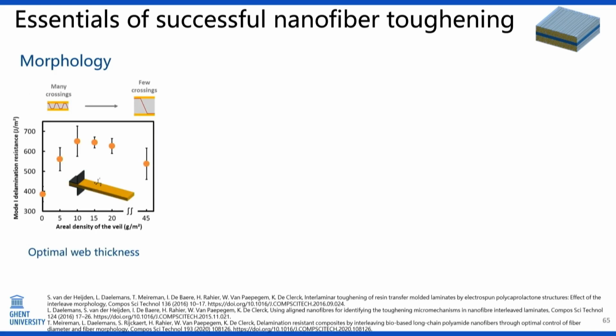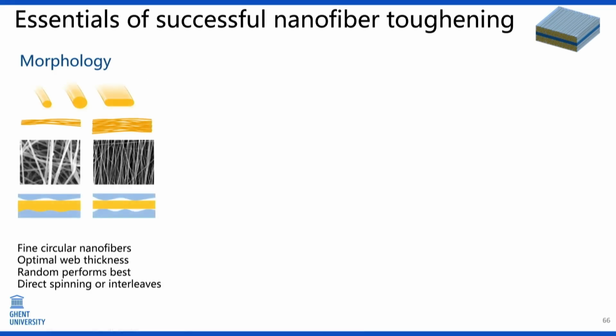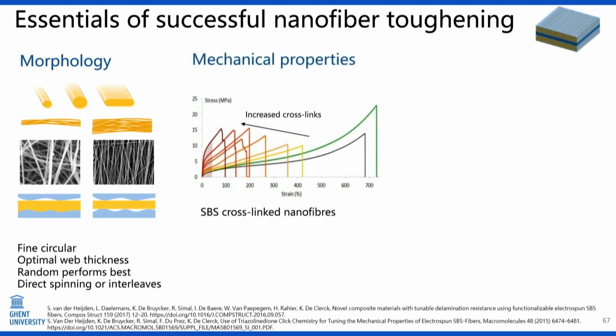Also, the web thickness can be optimized to have as many crossings as possible, because it's these crossings that give the nano-velcro effect. We've shown that random mats perform best. That's quite good, because that's the easiest to produce. And you can use both direct spinning on the reinforcing fiber layers, or you can use them as standalone membranes to introduce in between. Mechanical properties need to be optimized.